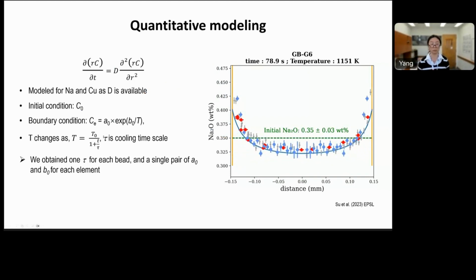The unknowns include this cooling timescale, and also a kind of empirical function for solubility. So the unknowns are A sub 0, B sub 0, and tau. For each element, we have a single pair of A sub 0 and B sub 0, but for each bead, we model for one single tau. So we performed those modelings, and we can obtain the cooling rate for each of the beads.